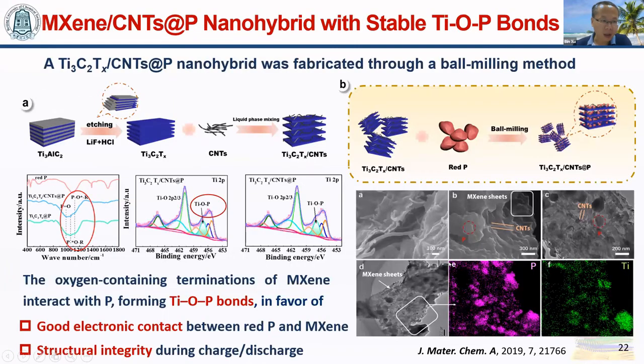In this work, we prepared MXene carbon nanotubes phosphorus nanohybrids through a ball milling method. The carbon nanotubes were introduced to MXene nanosheets to construct a conductive network, and then MXene and the carbon nanotubes were combined with red phosphorus by ball milling. During this process, the oxygen-containing terminations of MXene interact with phosphorus, forming Ti-O-P bonds. This bond favors good electronic contact between red phosphorus and MXenes. It also benefits the structural integrity during charge discharge.